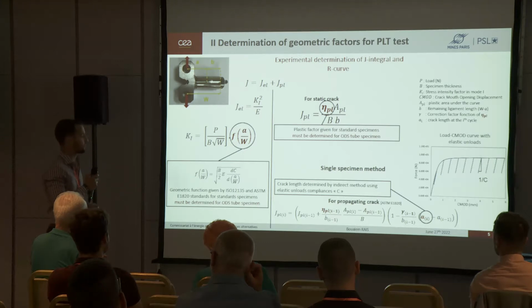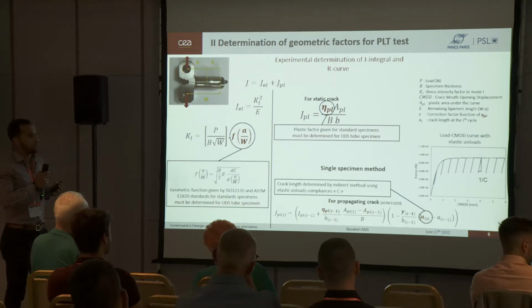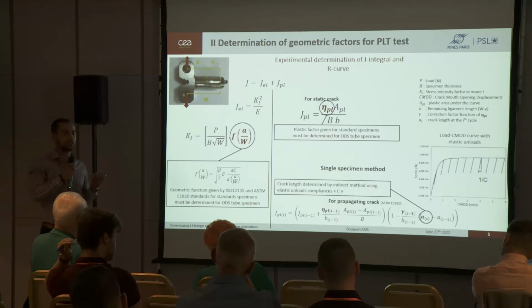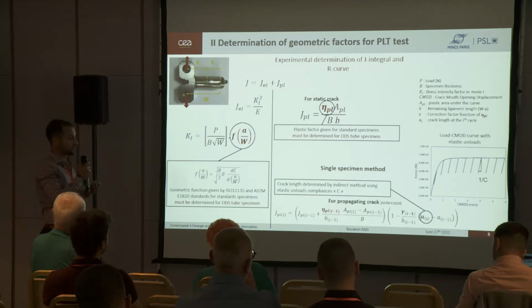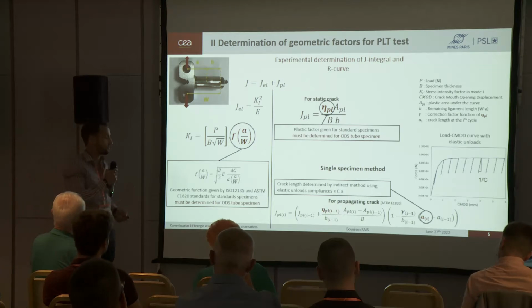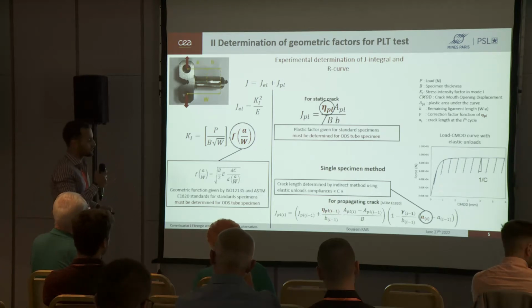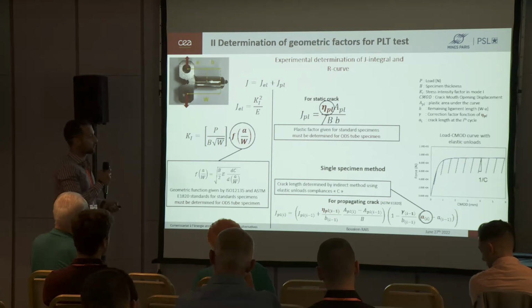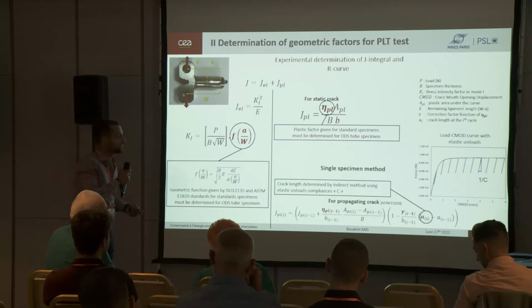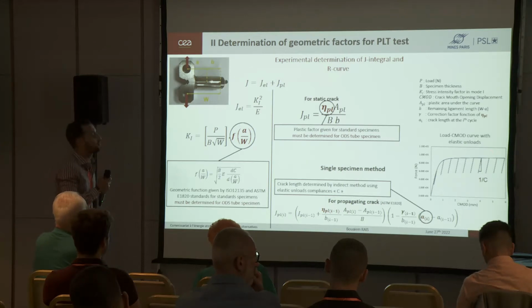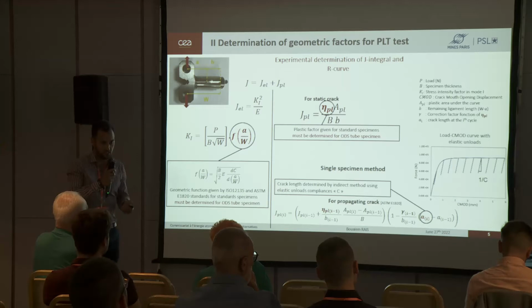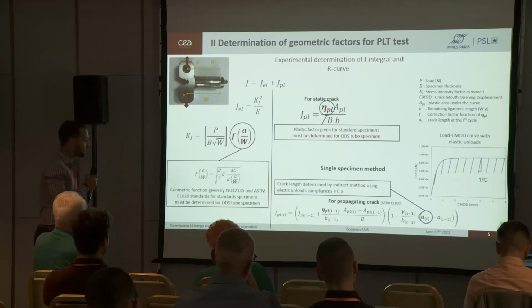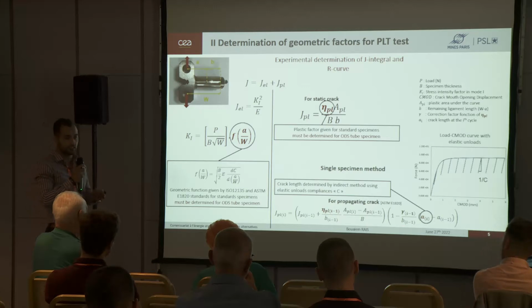So, because our material is precious, especially when irradiated, we use the single specimen method given by the ASTM standard. For this, we apply some unloadings during the test, and from the elastic compliance of these unloadings, we determine the crack length. This crack length will allow us to determine the crack extension and calculate the plastic J using this incremental equation for a propagating crack.